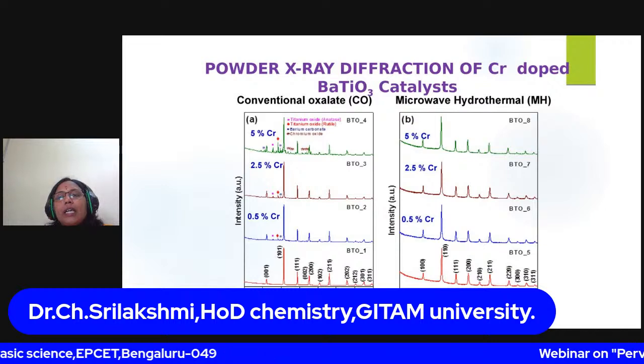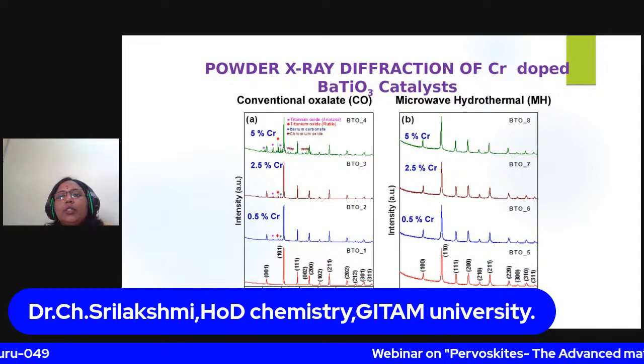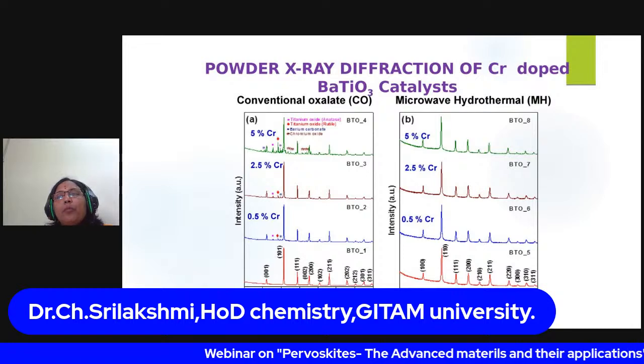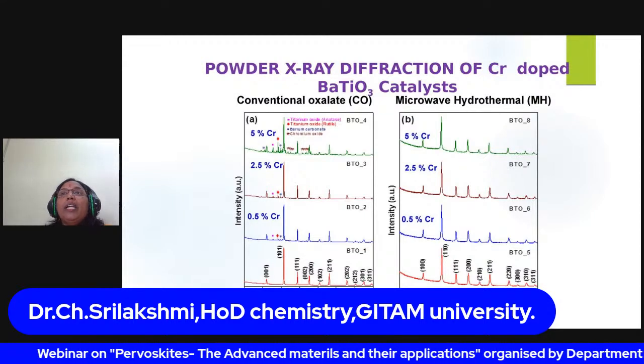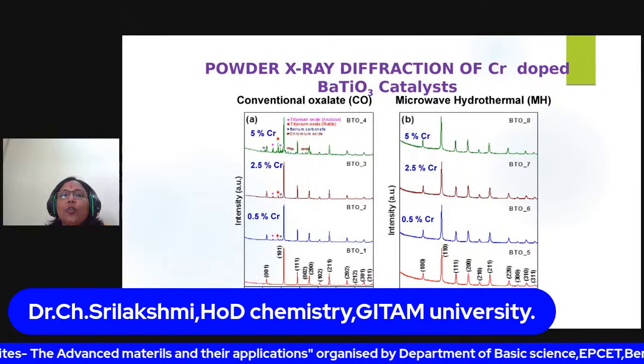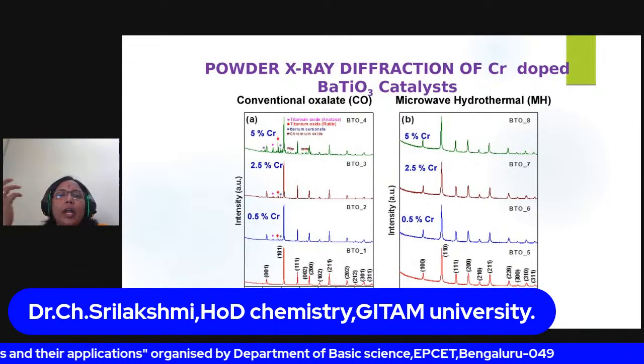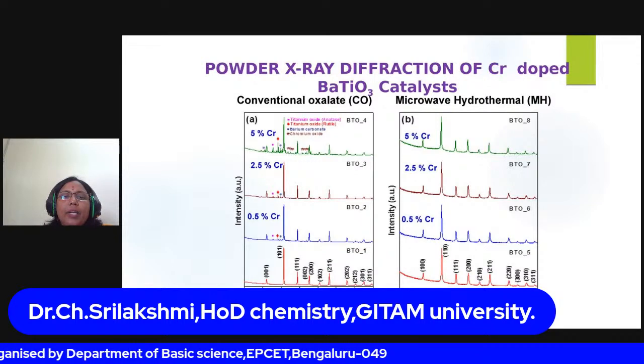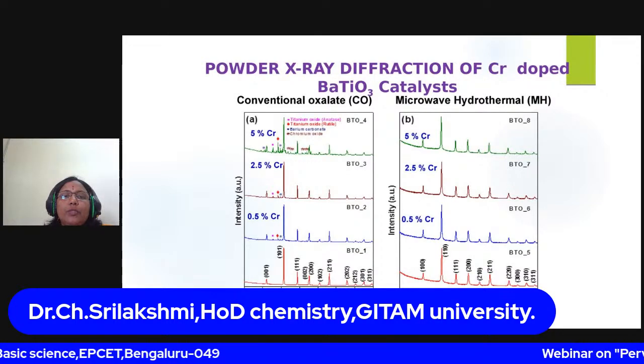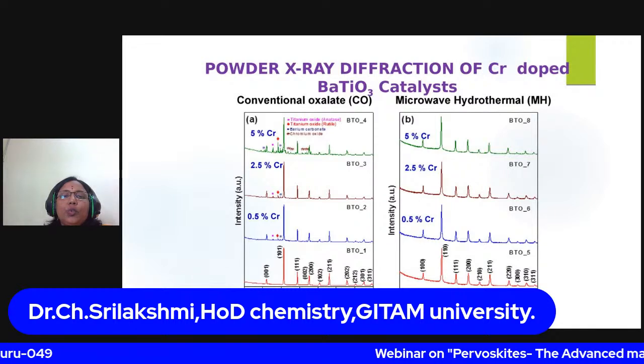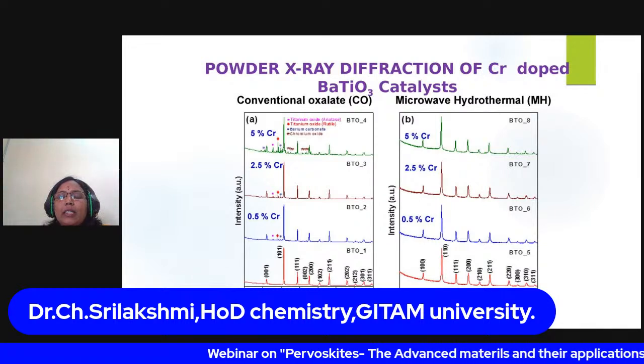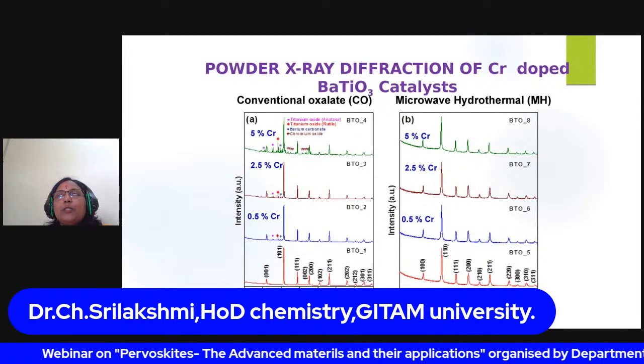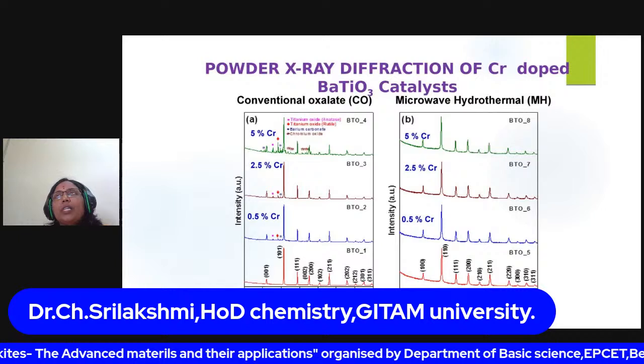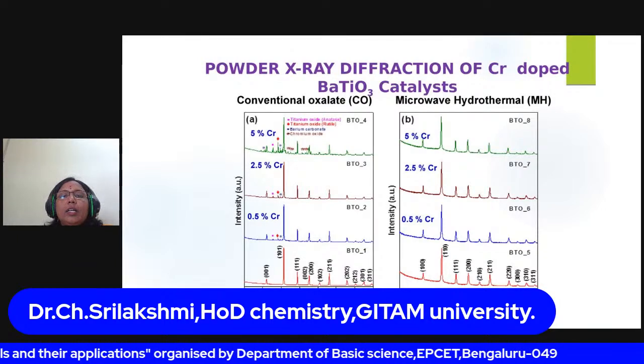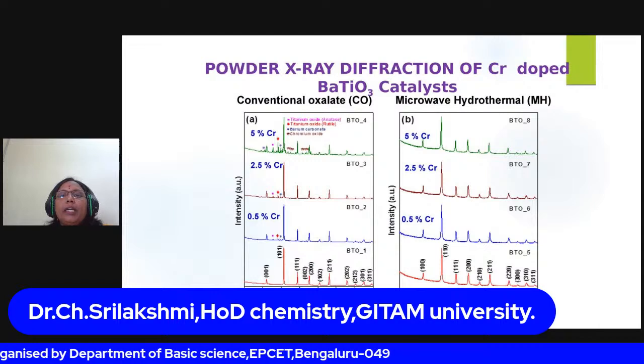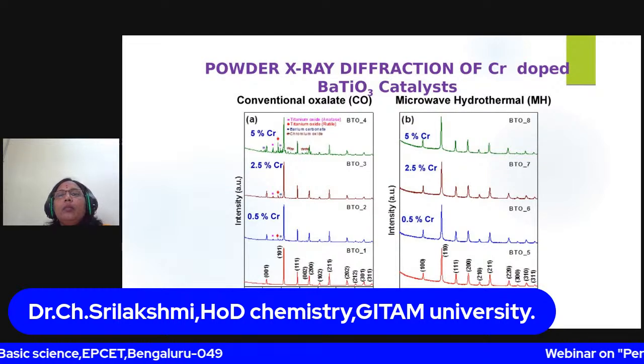Whereas in microwave synthesized samples, you can see, these microwave synthesized samples exhibit the cubic barium titanate phase, whereas in CO it is a tetragonal phase. How can we differentiate between tetragonal and cubic? There is a peak at 2 theta 45 degrees. You can see a split is observed, which corresponds to the 002 and 200 planes here, whereas at the same place at 2 theta 45, this split is absent in microwave synthesized compounds. That's how we differentiate the tetragonal and the cubic phases of barium titanate present in CO and microwave synthesized compounds.